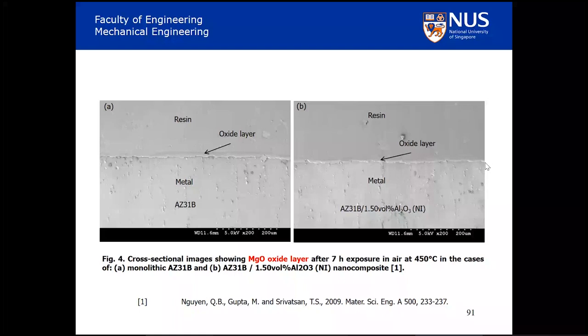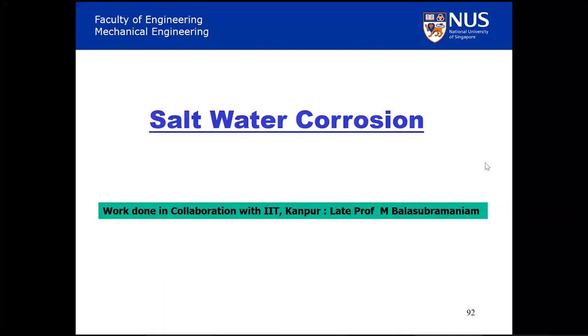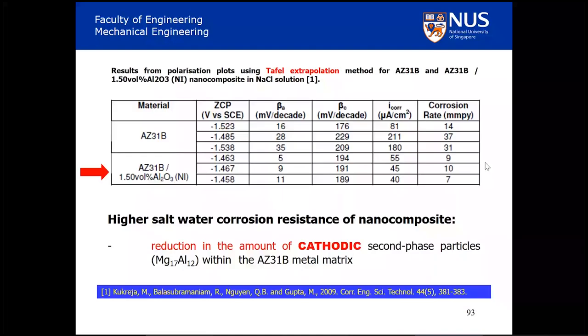Then we did some salt water corrosion resistance work with the late Professor Balasubramaniam at IIT Kanpur, and he indicated that putting 1.5% of Al2O3 or nano reinforcement can reduce the rate of corrosion by 1/3, and that he attributed to the reduction in the cathodic precipitates in the microstructure.